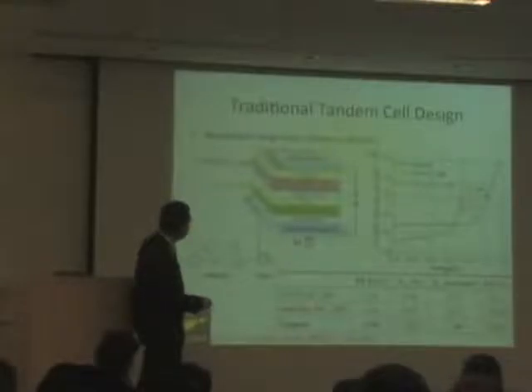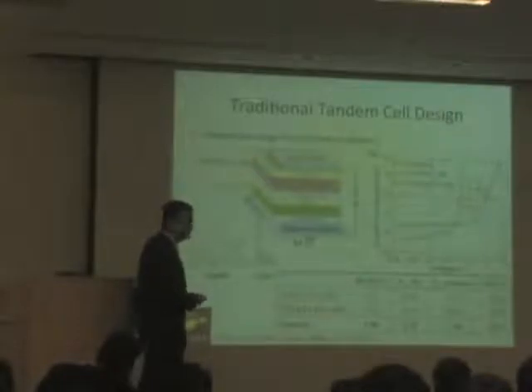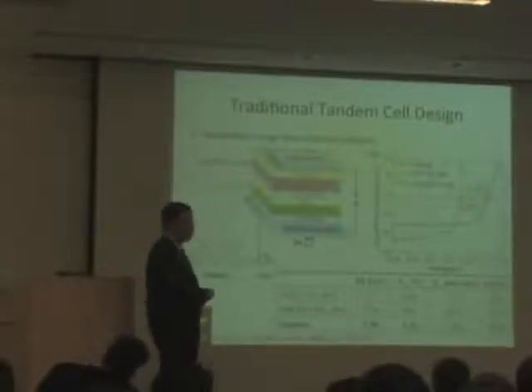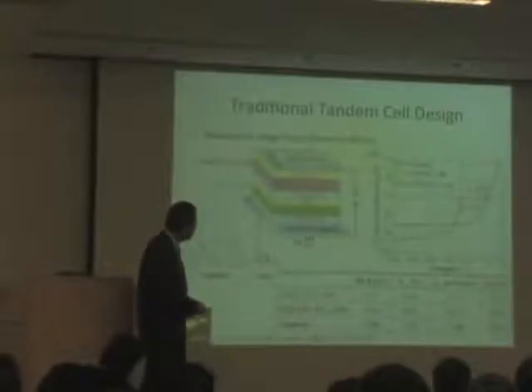So that indicates the VOC adds up, but the conductivity of the middle layer is still not there. We need better conductive materials, maybe another N-type semiconductor, because TiO2 is more or less like an insulator or photoconductor. The fill factor is not bad. The 63% is not bad. So we published in 2010.